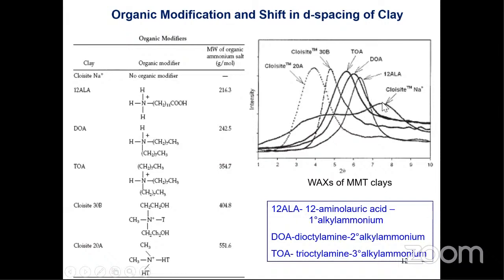Look at this. When you put different types of surfactants into the clay, the gallery spacing is shifted, the peak is shifted to lower angles. That means you increase the gallery spacing. This is what we do. My PhD students always do this: collect clay, react with surfactants, and increase the gallery spacing. Then the polymer can mix extremely well.